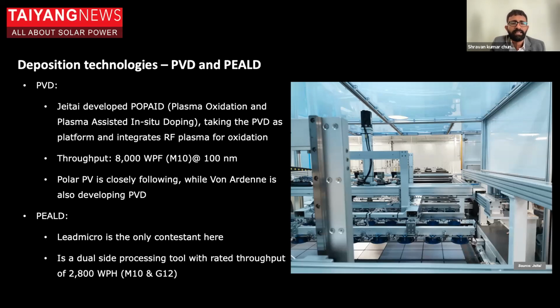Then PEALD is another interesting technology, which is essentially a combination of PECVD and ALD. Not so much information is available for this particular technology, because Leadmicro is the sole contestant here. What we learn from the data sheets is that it's a dual side processing tool. That means once you put the wafers into the reactor, it can do all the tunneling oxide requirements and the passivation requirements on the rear side, and then it also deposits the required passivation scheme on the front side. So it looks like it has low throughput, but when you really want to decouple the process, it can more than double the throughput.